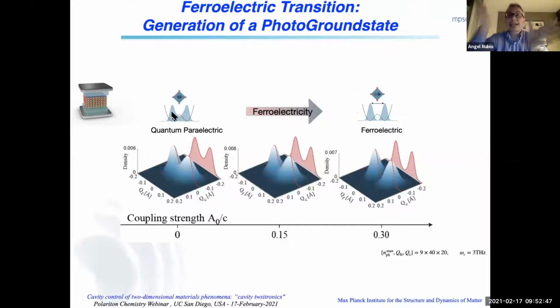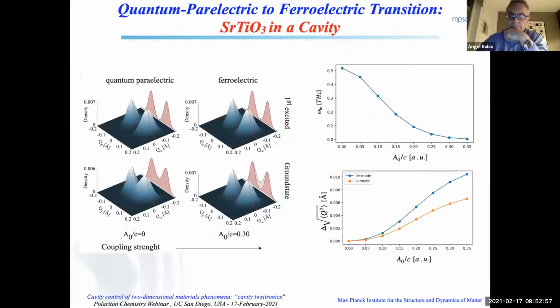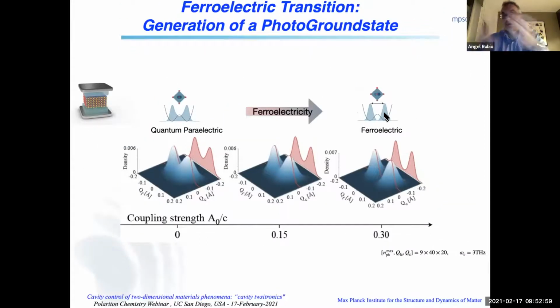And as you increase the coupling, what happens is that the barrier in between increases, and then the density is localized on either one or the other well, which is a linear combination because both are energetically degenerate. Then you have to be on the right or on the left, but there is a barrier. There is basically no overlap in between. And then you went from the quantum paraelectric to the ferroelectric transition.